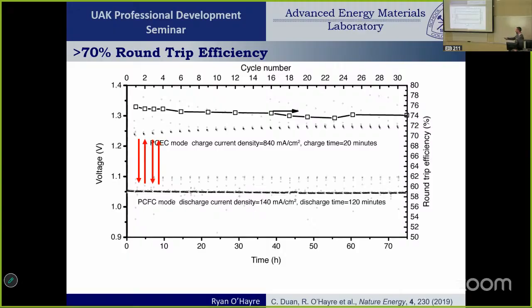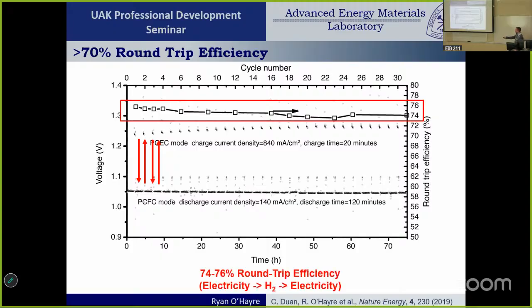And each time that we do one of these charge, discharge cycles, we measure how much hydrogen we're making, how much power we're producing, and we calculate the round trip efficiency, right? And so these data points up at the top, those are the round trip efficiency that we've calculated for each charge discharge cycle. And we did this 30 times over the course of about 80 hours. And you can see that it's pretty stable, a little bit of a drop off, but the round trip efficiency is on the order of 76 to 74%.